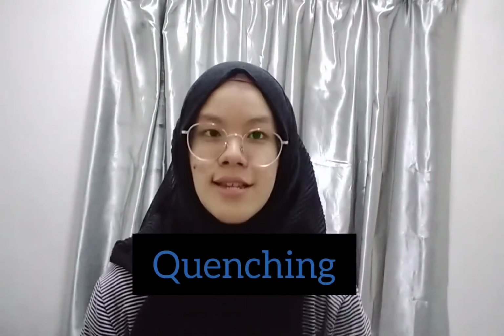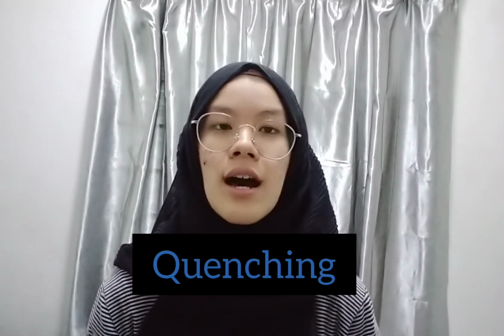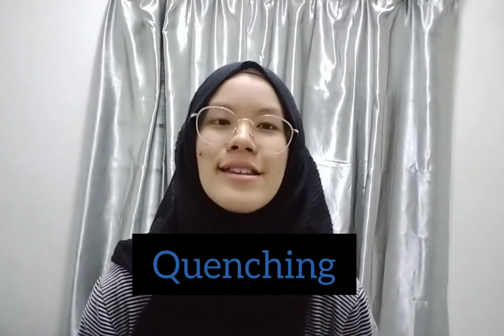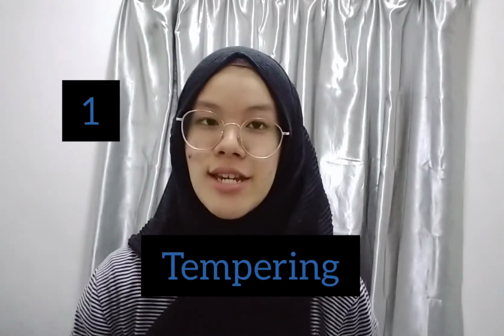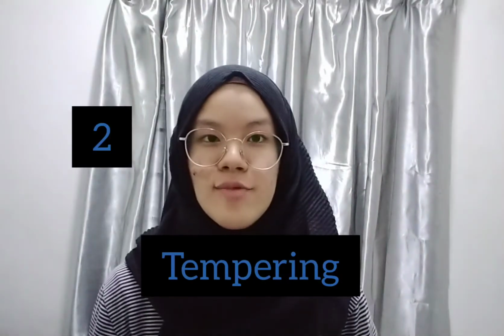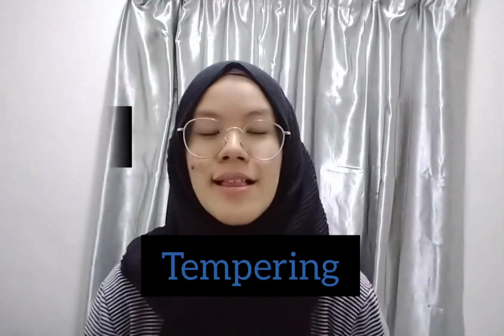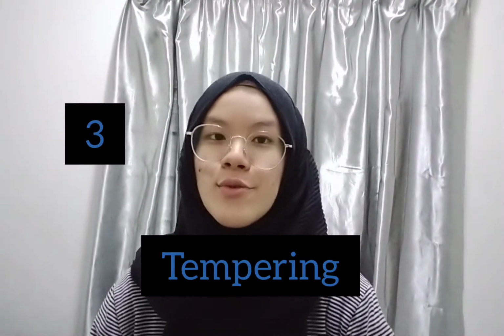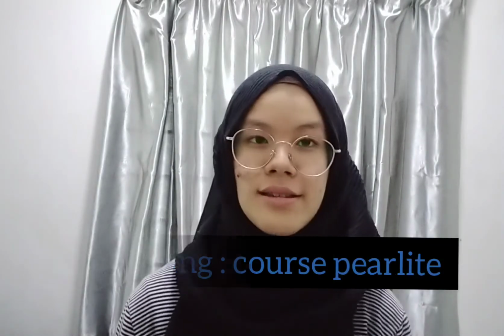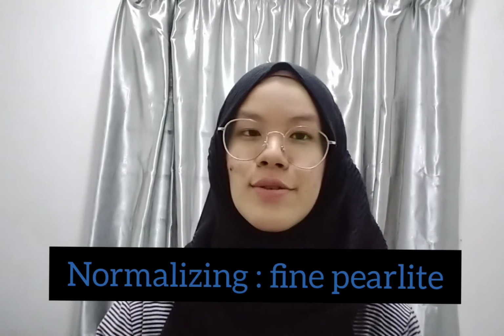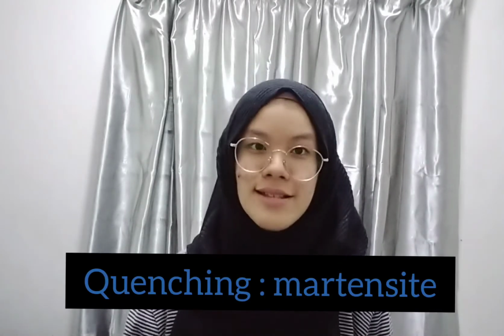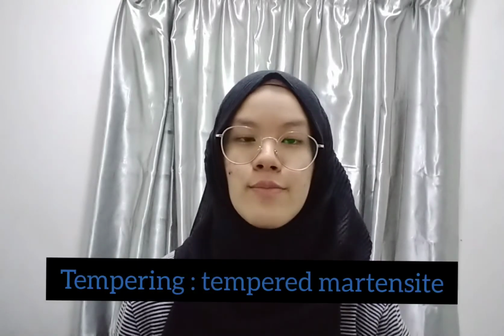Heat to 30 Celsius to 50 Celsius above the upper critical temperature and then quench. Immediately after quenching, the sample is heated and held at that temperature for about 2 hours. Lastly, remove from the bath and cool in air. For the final microstructure, the annealing will produce coarse perlite, normalizing will produce fine perlite, quenching will produce martensite, and tempering will produce tempered martensite.